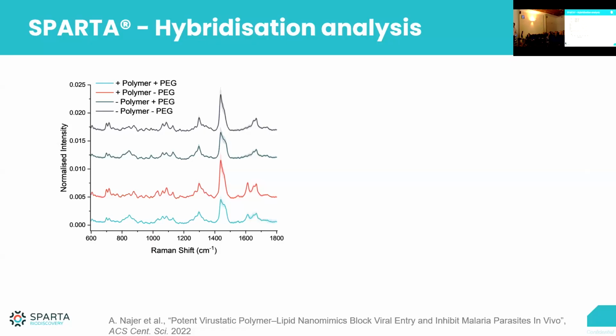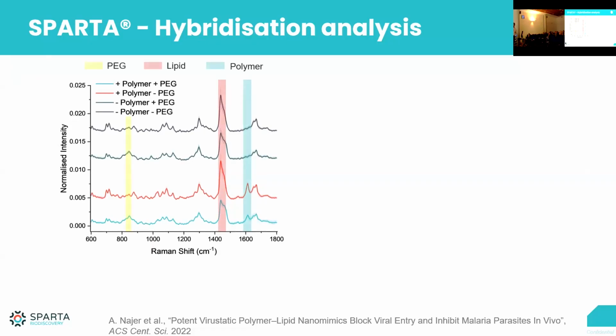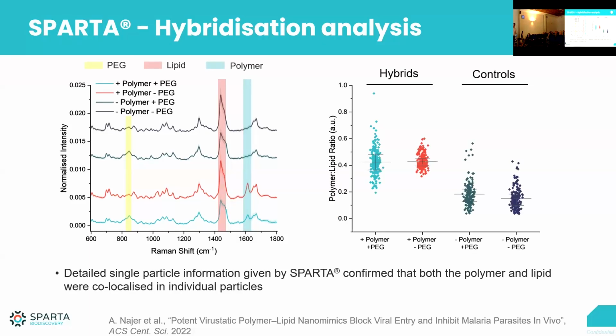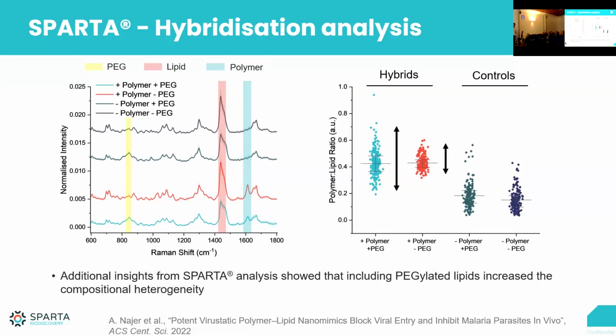So we do the Raman spectroscopy with SPARTA, and we can see here that when we have, for instance, polyethylene glycol incorporation, we can see that signal come up. And when we have the polymer incorporation, we can see that also very clearly. Crucially, we can determine from the Raman signal that most of these particles are actually hybrids. So we don't just have polymer and lipid-based particles separate in the solution, but we actually have combined hybrid particles that are all relatively heterogeneous in composition. And we can look at the variation within those particles as well.